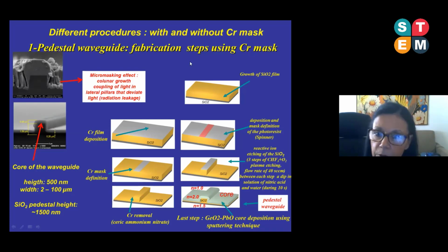When we use the chromium mask, we have the well-known micromasking effect, which is the columnar growth that surrounds the core and that compromises the guiding. In order to attenuate this effect, we reduce the thickness of the chromium mask by 70%, and we increase the number of steps to etch the silicon dioxide pedestal. In our case, we use 3 steps. And we finally obtain this better profile that can be seen here. Both images were obtained by scanning electron microscope.